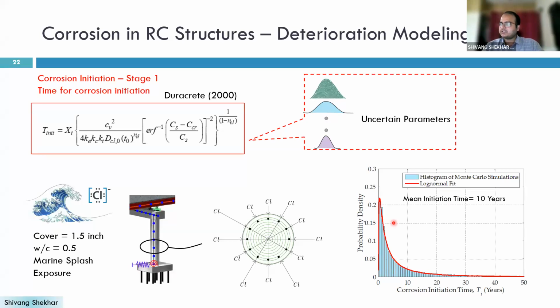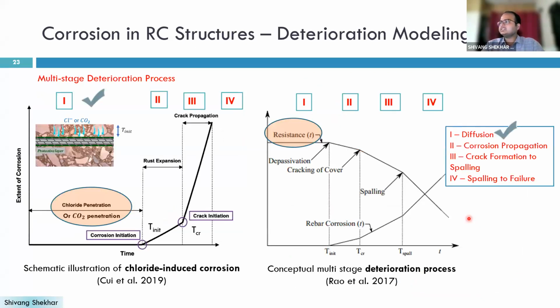Generally, for the numbers generated from Monte Carlo simulations, we fit a distribution, and here we are getting a lognormal distribution with a mean initiation time of 10 years, and obviously there is a deviation or coefficient of variation. Now this is your first stage. The first stage is diffusion. We try to find the initiation time for the corrosion of the reinforced concrete member based on the structural characteristics of the member.